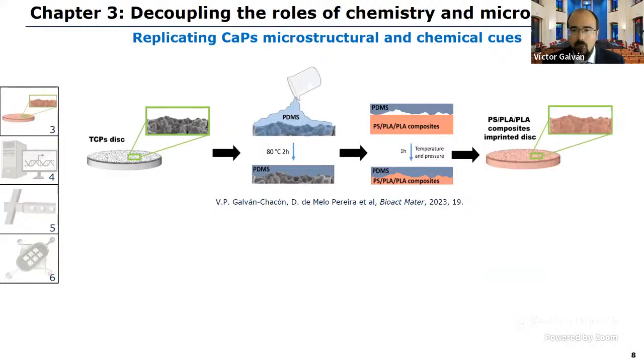So in chapter 3, we wanted to replicate the calcium phosphate microstructure and chemical cues and use this as a tool to decouple the roles of chemistry and microstructure. We started with a disk of tricalcium phosphate, and using a combination of embossing and soft lithography, we produced materials with the same structure, but in a different material, like polystyrene, polylactic acid, and polylactic acid composites containing some of the chemical cues of the original ceramic, like calcium salt, phosphate salt, or the original TCP powder.